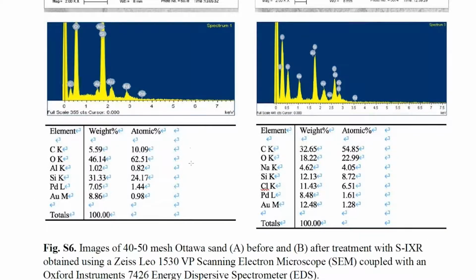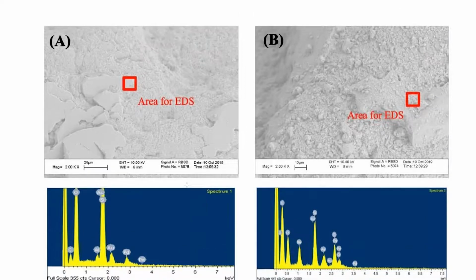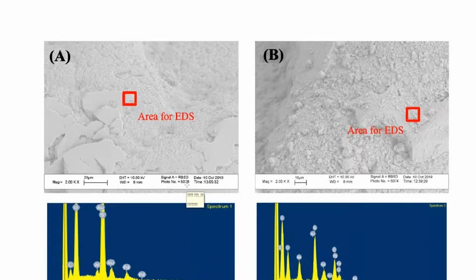So yeah, I was interested in the microscopy, and I'm glad you shared that. So it's evident just by visual inspection that it goes from a much smoother surface to a much more textured surface, and then you get the additional proof of the carbon spiking up, if you will, when the material is adhered to the sand grain. So that's very interesting. I'm glad you could share that with us, Kurt. Thanks for sharing that information, Kurt.